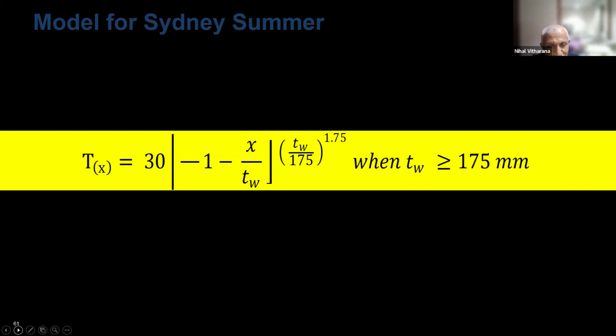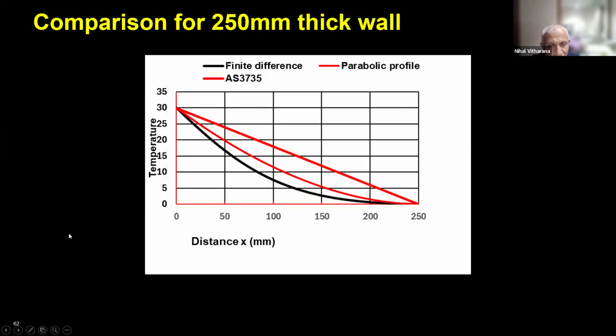Okay, let's go to the next one. So this is a 250 millimeter wall. The linear one is the New Zealand, 30 degrees. And then the black one is the finite difference, which I mentioned earlier. Then the orange one is a parabolic profile, which is close to the finite difference. And again, they tend to be linear. So if I put 175, all those three curves become linear, similar to the New Zealand standard one. Yeah, next one.